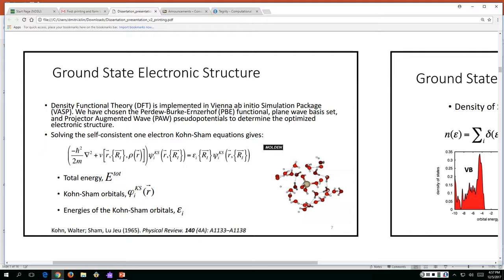So in looking at the charge carrier dynamics of the system, the bottom 4 left initial conditions correspond to the 4 strongest electronic transitions in the ground state. So there's some type of initial excitation going from, say, 155 to 180, that top left panel, and then the corresponding relaxations for the hole and the electron occur over a time period of about, sorry, it was about 6.5 picoseconds. And so both the electron and hole are found to relax at a very similar rate, and so the charge carrier separation lifetime is not very large.